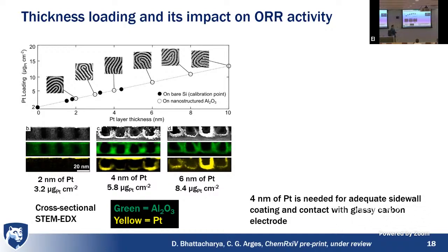Then we went ahead and put down 4 nanometers of platinum. So we're over here now. We're at a higher loading. From a top down view, more or less these images look the same. So that's why you have to do this cross-sectional imaging. We start to see the platinum coat the sidewall. And then we did 6 nanometers, right?